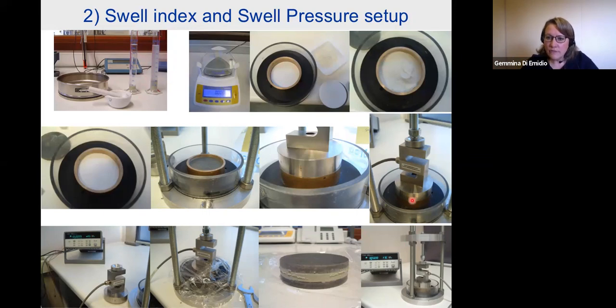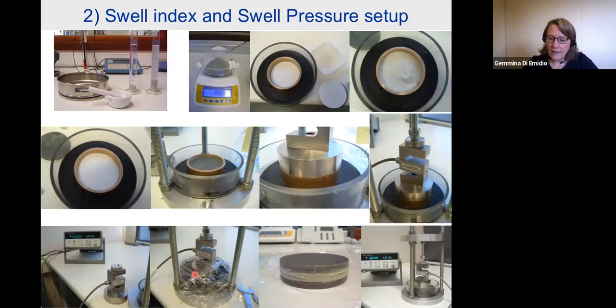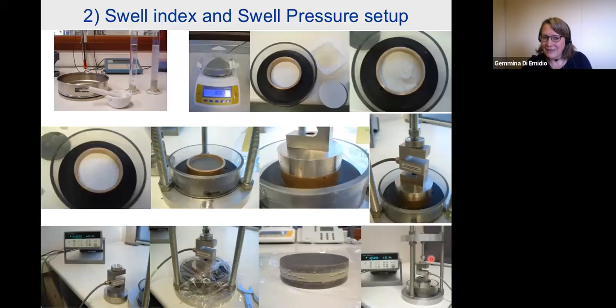At Ghent University we developed a swell pressure apparatus to address this limitation. It is simply an oedometer where bentonite powder is placed between two porous stones; the height is fixed with a load cell, and after inundation with a solution we measure the pressure of the clay platelets on the load cell. This pressure represents the force that swollen water exerts between the clay platelets — the higher the swell pressure, the higher the possibility of a dispersed structure, which is what we want — without the limitation of turbidity.